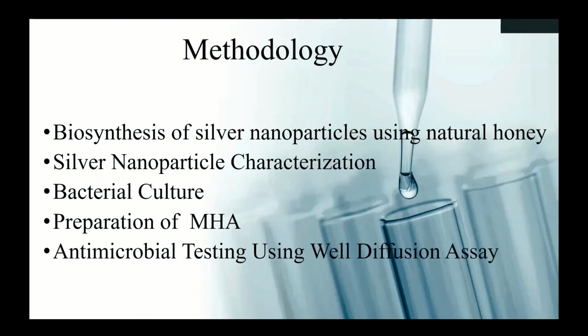So we made our nanoparticles using the honey at different concentrations. The one we worked with was at 50%. We made our solution of silver nitrate. We cultured our bacteria. We prepared our Mueller-Hinton agar for the bacteria to grow. And then we did the antimicrobial testing using the well diffusion assay. Next slide.